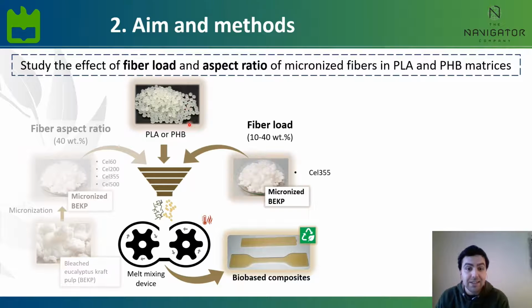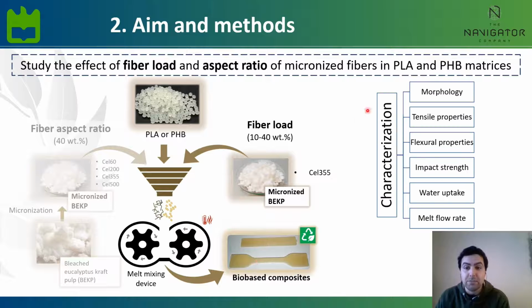To study the influence of the fiber load, we used one of the micronized fibers with an intermediate aspect ratio, and that was cellulose 355, and we changed the reinforcement load from 10 to 40%. Finally, all these composites were characterized regarding their morphology, tensile, flexural, and impact properties, water uptake capacity, and melt flow rate.